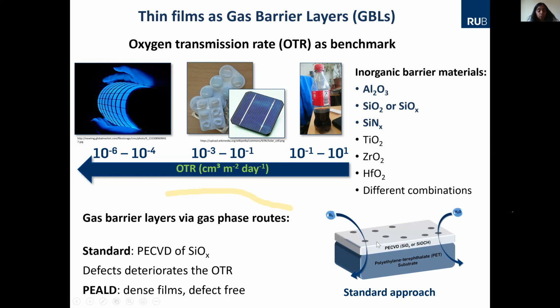On the other hand, for cost efficiency, you also need a process where you can make it cheaper. And PECVD has been well established for decades now to coat, for example, Coke bottles or the pharmaceutical covering materials. In that case, you have a coating of SiOX. And when you actually look into the PECVD coatings through a microscope, you can see there are some defects. Basically, there are pores. So I call it defects. This is a porous film. It may not be full of pores, but certain pores may exist because the coating time is pretty fast.